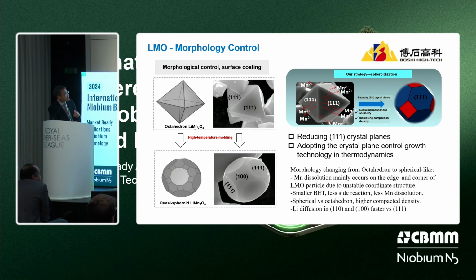And compared with this one, you have a higher compacted density. You can increase the compacted density. And for lithium diffusion, in different phases, different lattice planes, actually, in this one and also this one, the diffusion is faster compared with this plane. So you can decrease the powder resistance.